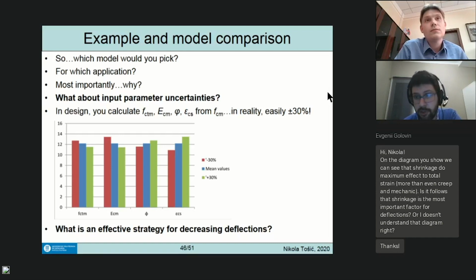But they are huge for slabs, for example, whose service load is usually close to the cracking load. Imagine your predicted tensile strength shows the slab will be uncracked with a very small deflection. In reality you don't cure the slab well, there's lower humidity, so you get a lower tensile strength and a lower cracking moment. It cracks and the deflection jumps because now you're interpolating between a cracked and non-cracked slab, and the difference is huge for a small difference in the parameter value.